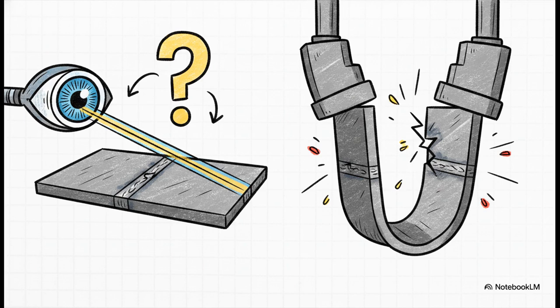Because the metal didn't melt, flaws like kissing bonds don't have an air gap. They lack a volumetric gap. That means if you shoot an X-ray through this weld, conventional radiography will look right past it and tell you the weld is absolutely perfect. They are essentially invisible. Because of this, you literally have to physically bend the metal. Destructive bend testing is mandatory, just to prove the bond is actually real and won't fail in service.